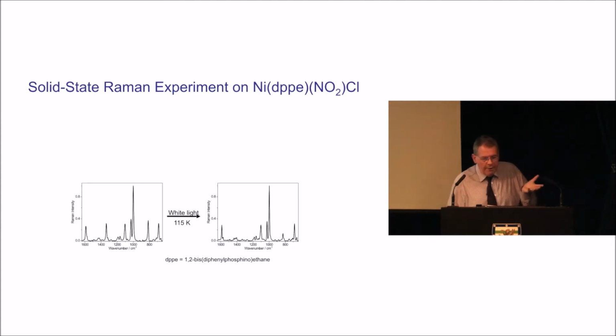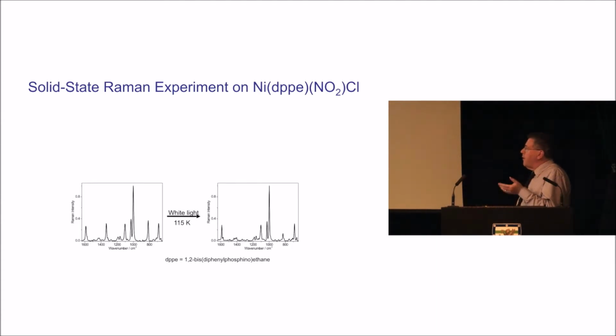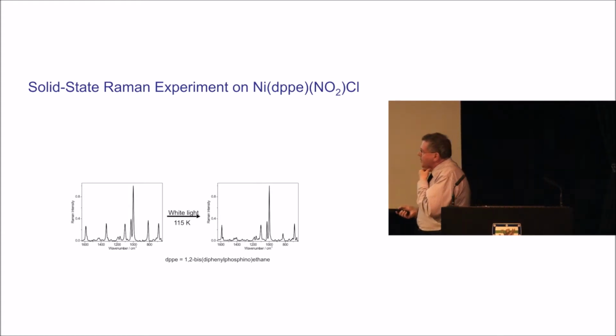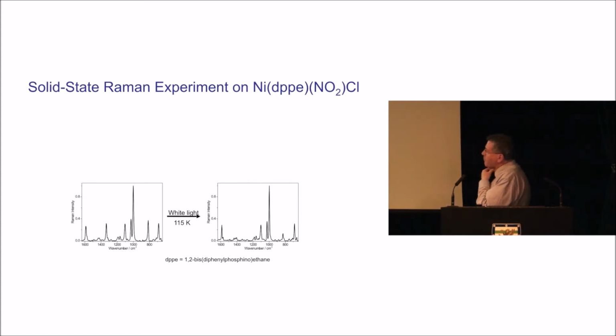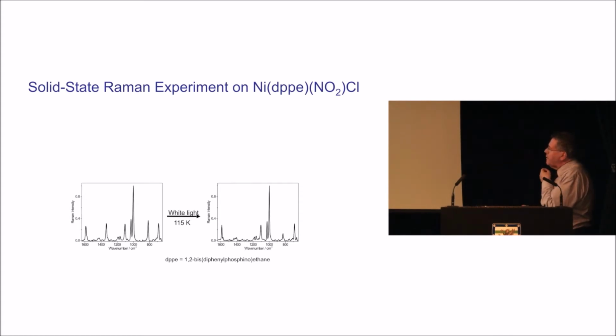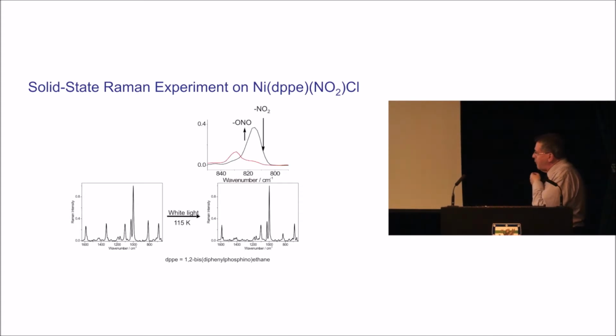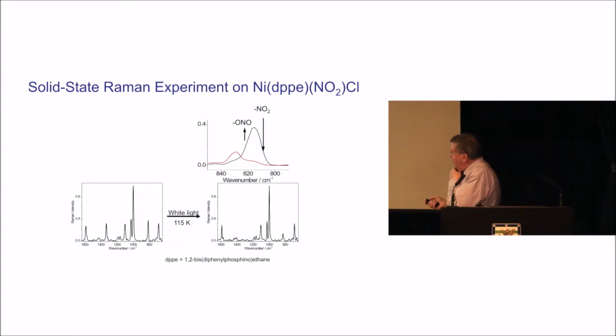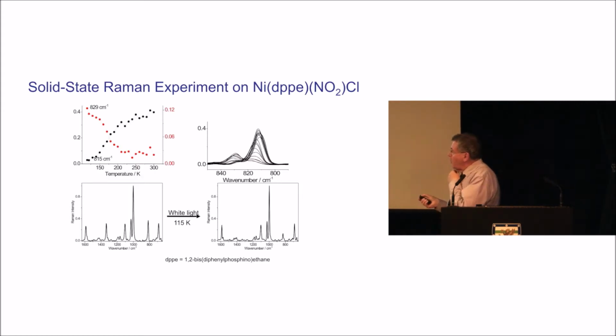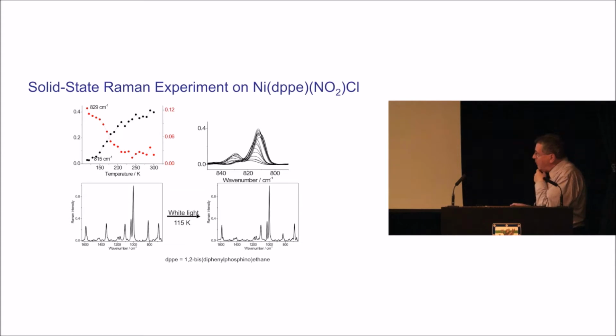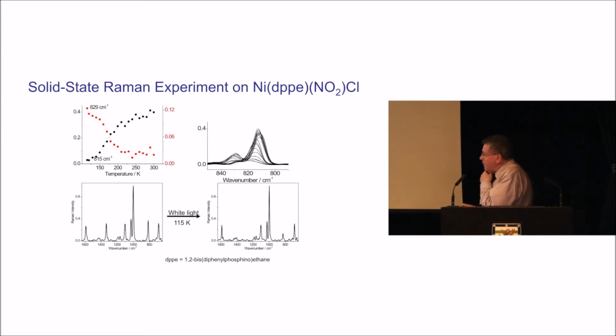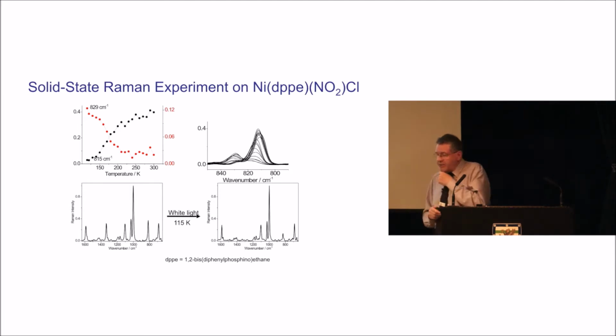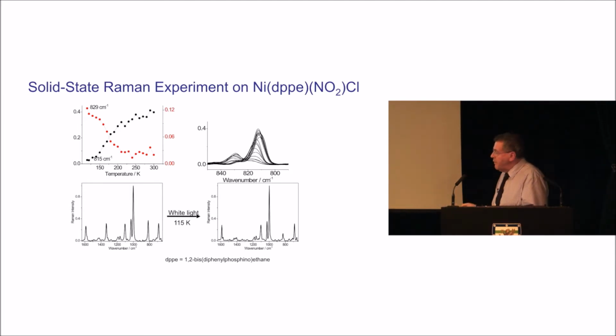We always combine our experiments with spectroscopy, and we looked at the Raman of this system, and you can see that there's actually a change around 800 centimeters to the -1, sorry, with white light, which suggests there might be a change. And in fact, if you do this over time, you can actually see the interconversion of one band rising and one falling. And in fact, you can also look at the temperature range and again see those bands changing. So it looks as if something happens in the solid.